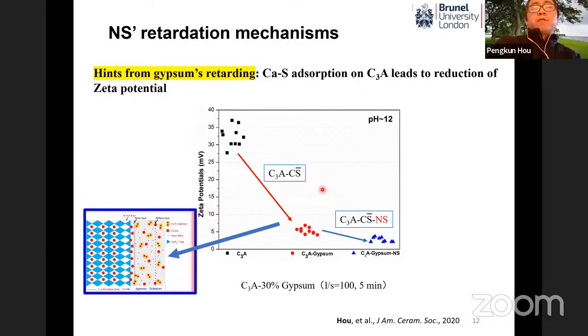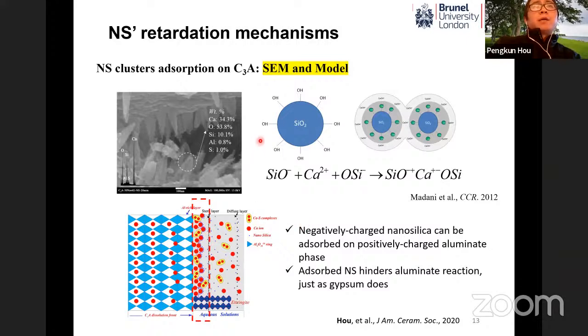And when we further add nanosilica into the system, we can see a further reduction of the potential. This actually makes us think whether nanoparticles can act as a kind of gypsum in the C3A system. So to do that, we make an observation of the C3A plus gypsum plus nanoparticle system. We can clearly see that nanosilica clusters were adsorbed onto the C3A particle surface.